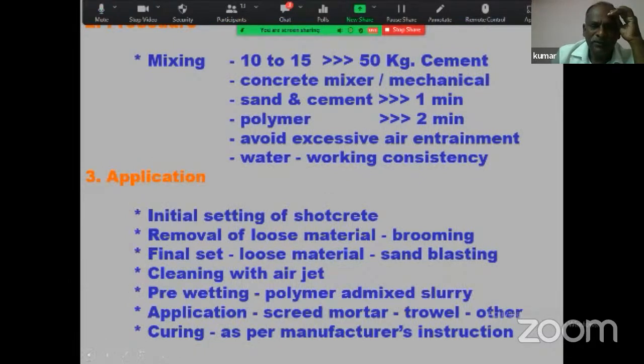Then properly mix 10 to 15 per 50 kg of cement in a concrete mixer, and polymer, both the things blended together, the material mixing is done. How is it applied? Initial setting of the shotcrete. When the shotcrete got cured, the final setting time is 10 minutes. After that, you have to make a removal of loose material by brooming. The surface is to be properly cleaned, whatever loose material is not adhered on the base shotcrete has to be removed.